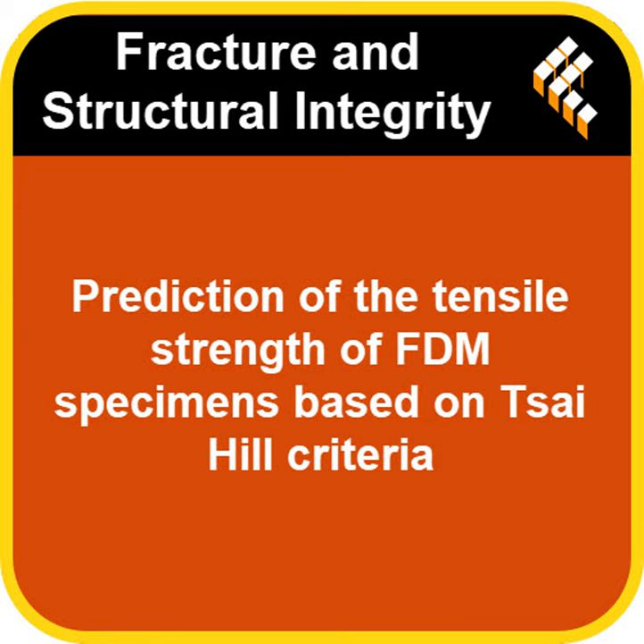They used two methods, actually. One was a standard mechanical extensometer, basically a little clip-on device that physically measures how much the part stretches between two points. Okay, the standard way. Right. But they also used digital image correlation, or DIC. This is a really neat optical technique. You spray a random black and white speckle pattern onto the surface of the sample. Like random dots. Yeah, just a random pattern.